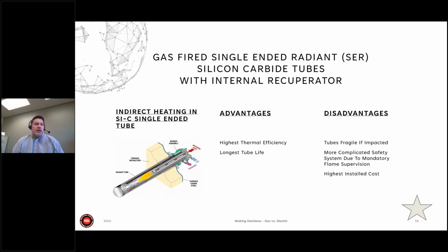Now, noting that the longest tube life, you're removing the high temperature thermal creep of the alloy radiant tubes that you have. So it's eliminating that. That's what helps extend the tube life. But the tubes themselves are fragile, and you have to take care not to have any mechanical contact with the tubes. And there are still safety system requirements for mandatory flame supervision that get a little complicated with the silicon carbide tubes. And just the cost of the silicon carbide tubes themselves makes this option the highest installed cost.